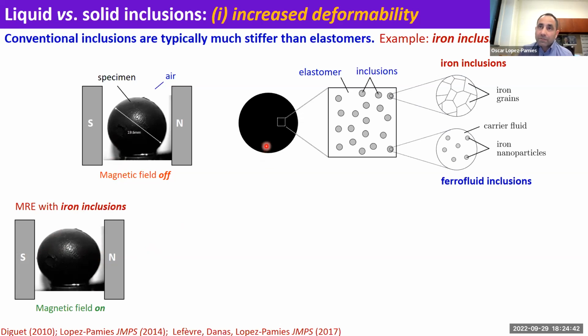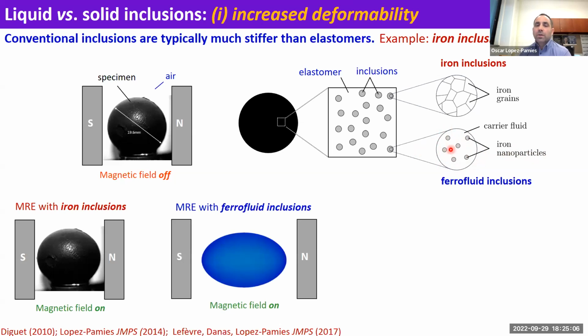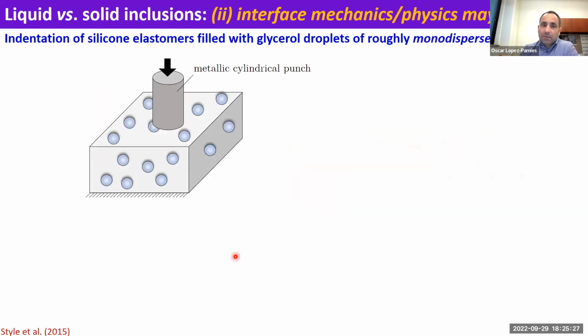Alternatively, if you want something that is sensitive to magnetic fields, you can use ferrofluid inclusions. These essentially are oil, or a fluid, typically oil with nano iron particles. This is sensitive to magnetic fields because of the iron, but it's a fluid, and therefore it deforms a lot. So if you run a simulation with ferrofluid inclusions as opposed to iron inclusions, you can get very significant deformations, which for some applications may be what you want, right? So the idea is with liquid inclusions as opposed to conventional solid inclusions, you may increase deformability.